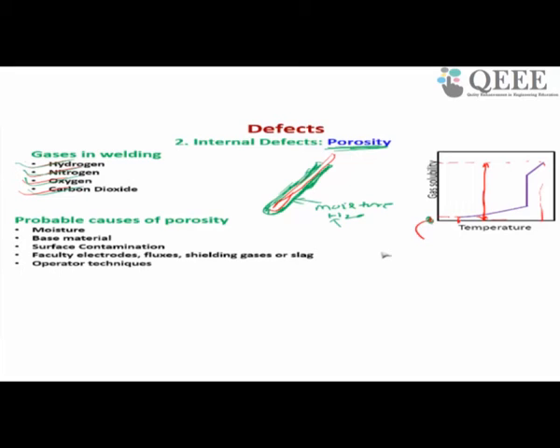But even after doing that, there is a high chance that hydrogen may still be entrapped in the material. For example, when you use shielded metal arc welding, generally we use a filler metal which is coated with flux material as well as shielding gas material. Generally they keep it in a fridge or at low temperature before using. So there is a high chance that it may contain atmospheric moisture, and moisture contains water.